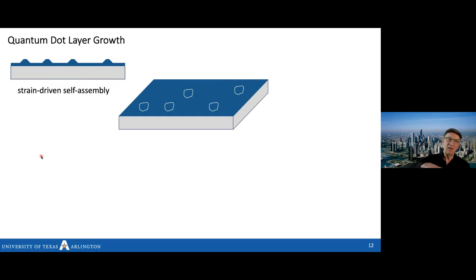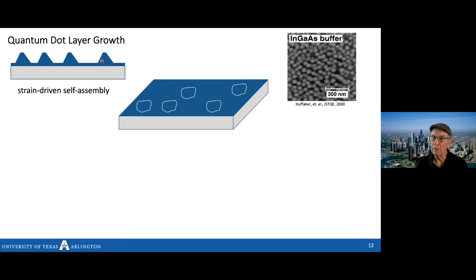So what started out as layer by layer, and that's how unstrained materials grow, becomes sort of collective. The energy changes such that it's more likely to grow up than to grow out. So what started out as a thin single layer becomes a very thin layer with these larger pyramidal looking quantum dots on it. And here's an image of quantum dots done by our EE department head, Diana Huffaker, in her earlier life. And what you can see is these dots are clearly different.